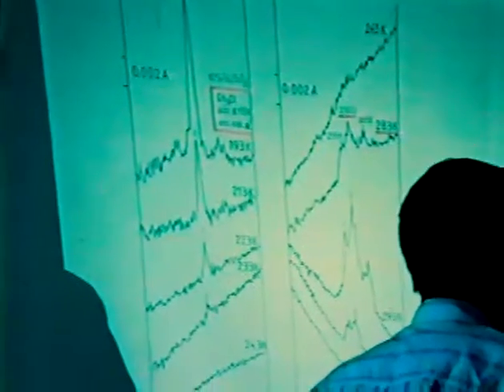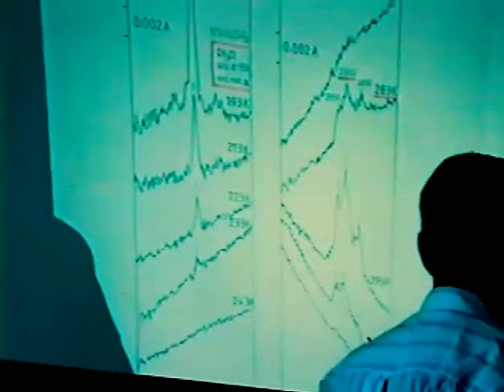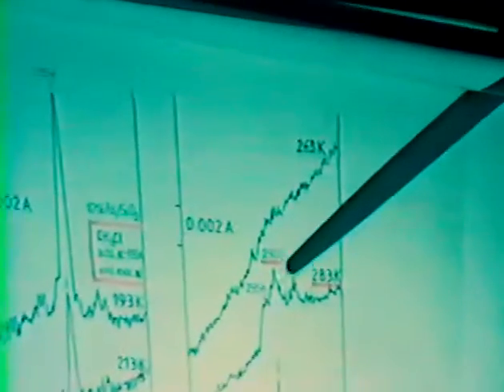A different kind of experiments were performed as follows. After adsorption of methyl chloride on palladium silica catalyst, the gas phase was evacuated. The band at 2954 centimeters remained only on the spectrum. This band decreased with the increase of temperature, and at a given temperature completely disappeared from the spectrum. Very surprisingly, however, at this temperature, the bands in the CH region reappeared.